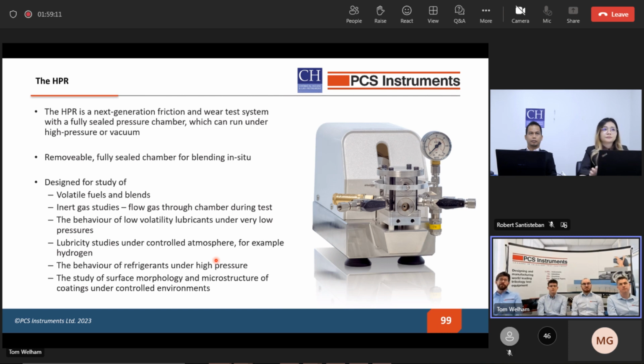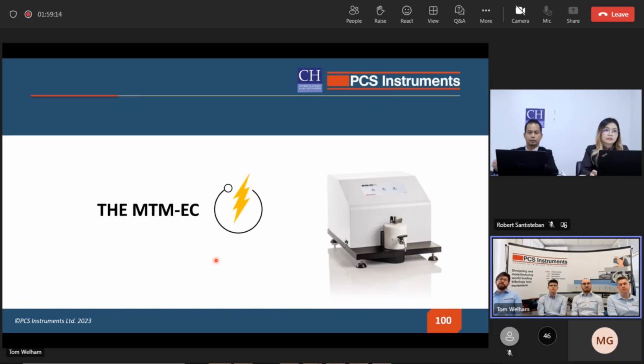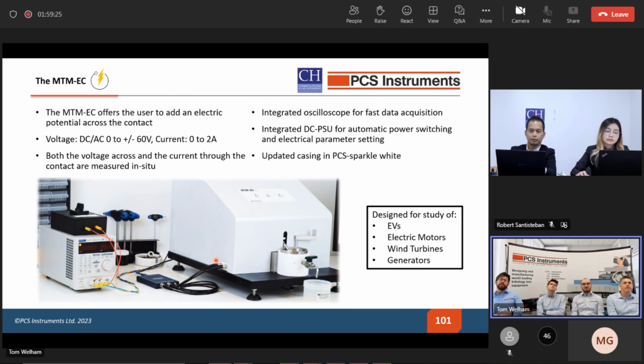The second rig I want to talk about is the MTM-EC. This is a modification to the MTM and could be bought as an entire unit or as an upgrade for existing MTM systems. It consists of electrical potential across the contact, which is controlled using the PCS software. You can apply both a DC and AC voltage, plus or minus 60 volts, and currents from 0 to 2 amps. Both the voltage and current throughout the entire test are measured in situ, so we can get an average voltage measurement of the contact throughout a timed Stribeck or traction step.